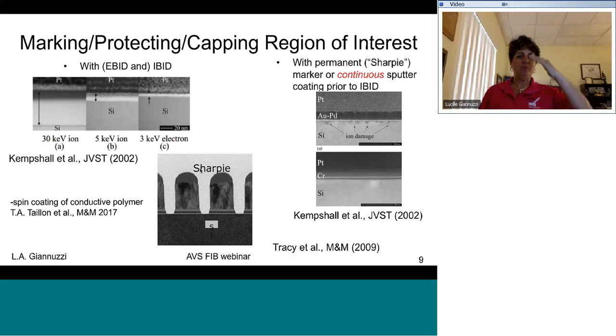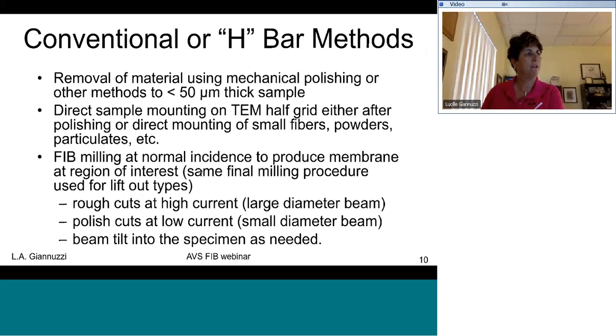Okay, so again, it comes back to this. You want to definitely protect your layers of interest. So if you've got something that's right up against the surface of your sample, don't even turn on the FIB until you've protected it, either with electron beam deposition, sputter coating, Sharpie, or conductive polymer, or some other way.